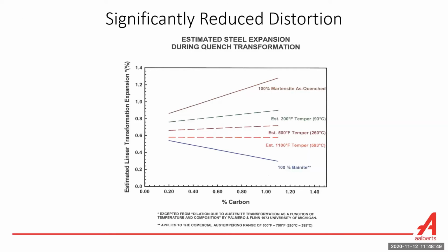One of the other aspects that we have found highly beneficial to the salt quench process is reducing distortion. I could get into the microstructural reasons, but you can see here that the linear transformation expansion of bainitic steels is dramatically lower on a percentage basis than 100% martensitic. Anecdotally, I can give an example. I can't show this, but I can talk about it. We had a customer approach us. It was a pump shaft, 18 inches long, 3/4 of an inch in diameter, and they were trying to hold 5 thousandths of runout over the 18 inches. They were oil quenching and tempering the part, and they couldn't hold 30 thousandths of runout. We successfully Austempered the part and were able to hold it within 5 thousandths of runout. It's because we're creating a preferred crystal structure that does not distort as much.